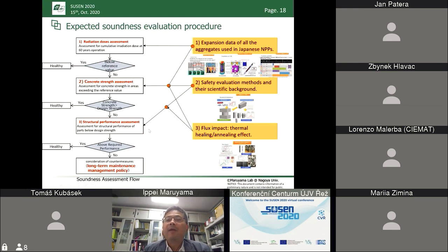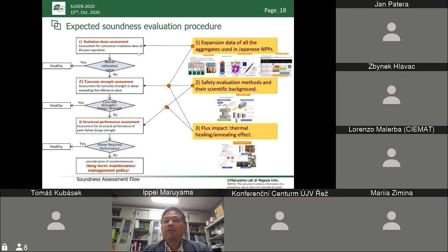As I mentioned, limestone has an ionic bond, and it's very tolerant to the neutron irradiation, and it doesn't show any expansion in the range of the realistic neutron fluence for the light water reactor. Therefore, this kind of reference level is a function of the rock-forming minerals or the rock itself. So we have to do some additional experiments. And when we want to evaluate the concrete strength, we have to evaluate this theoretically. So once we have the relationship between the neutron flux and the reduction ratio of the compressive strength, that is very helpful.